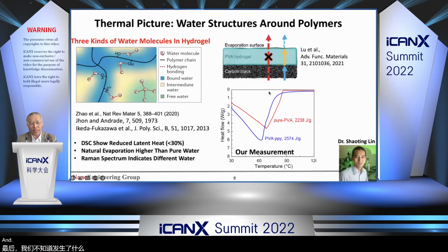And at the same time, Professor Yu had a lot of very interesting results, and I mentioned they have this three water picture. And one experiment really intrigued us. In this experiment, they put a pure polyvinyl alcohol hydrogel on a carbon paper. And in this case, to our opinion, pure PVA does not absorb sunlight. So sunlight gets to the back carbon and they heat up. So that's the thermal effect. So probably they're right. And we also did some differential scanning calorimetry, and sometimes you could see reduced latent heat. Professor Yu's group reported it, but the latent heat reduction can never really come to the level of the experiment, because it's only less than 30%.